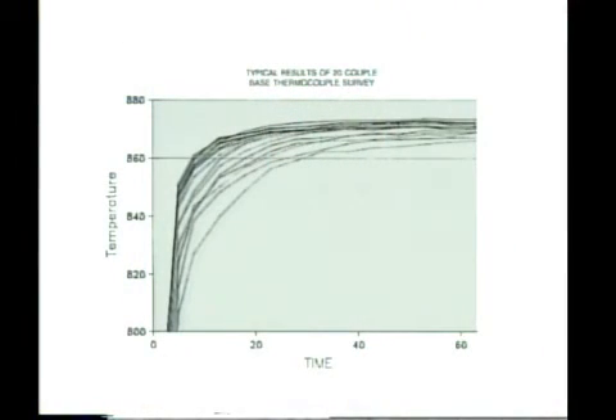into a pre-stabilized furnace. The thermocouples are then read for a period of time, usually 30 minutes to 1 hour, to ensure that the furnace maintains the proper temperature tolerance throughout the work zone. Readings are taken usually at either 2 or 5 minute intervals during the furnace recovery and soaking period. A complete history of the survey record should be recorded and filed.